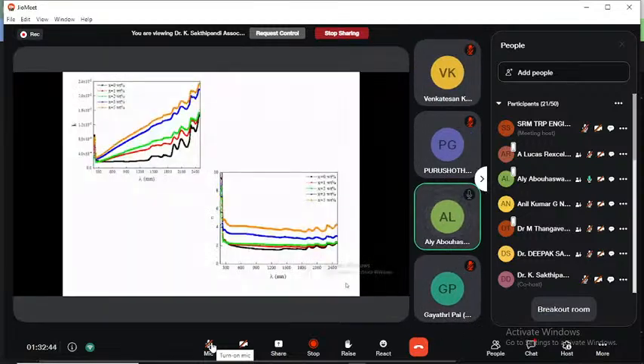The decrement in the case of direct and indirect energy gap is due to the vibrations that happened at polymer disorder level, which appear as the result of polymer frame alteration caused by nanofiller, and also due to the increase of the localized states in the band gap. This helps to improve the carrier interaction in the valence and conduction band.